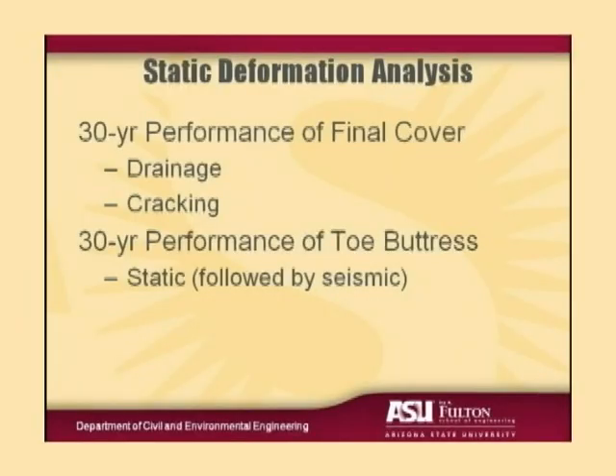We also did a very sophisticated static finite element analysis to try and predict the 30-year performance of the final cover. The concerns there are maintaining drainage grades and cracking of the soil cover on the north slope, and also to try and predict the 30-year performance of the toe buttress, both statically and what would happen if, after 30 years of settlement, all of a sudden the toe buttress got hit by the design earthquake. So we superimposed the seismic loading on top of the static deformation after 30 years.